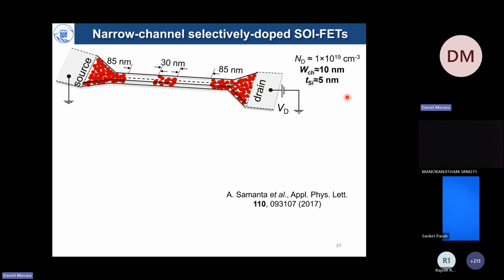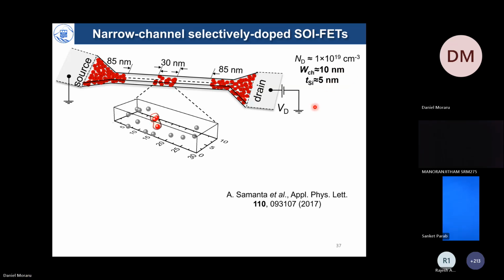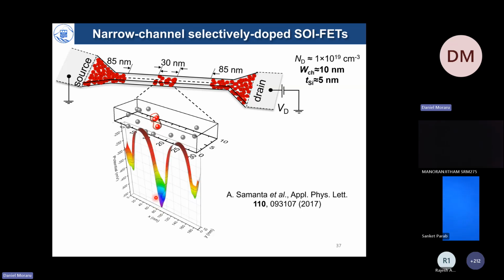A second idea was to make the nanowires very, very small, width and thickness just a few nanometers. So in that case, we have a few dopants coupled here as molecules, giving rise to a very deep potential well in the center between source and drain. And the key point here is that we are now limiting the transport to just one unique transport path. So we have to flow the electrons exactly through one quantum dot and move it out, while transport through nearby areas is impossible. It's covered in insulator. So this work was done with Dr. Arup Samanta, now associate professor at IIT Roorkee, and he was a postdoc in my lab around that time.